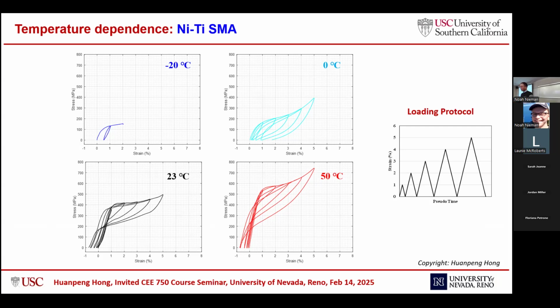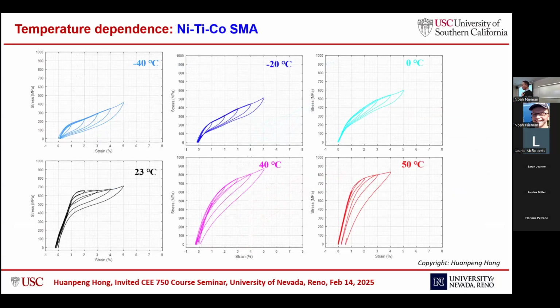What is not very good is that when the temperature drops to 0 Celsius, this nickel titanium alloy starts losing the shape recovery capacity. After we unload it from 5%, the residual strain is around 2%. That means this material is losing its function. Down to minus 20 Celsius, it behaves almost like a regular steel. So we pause the test. So this is the nickel titanium cobalt alloy.